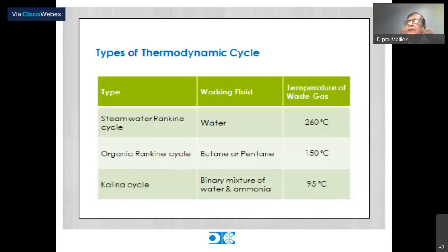That's true. But within this framework of temperature boundaries, there are other technologies which are also getting developed. One is, instead of using steam as a working fluid, we can use ORC, which is called organic Rankine cycle, with pentane as working fluid. There are quite a few plants, and a new Kalina cycle has also been developed, where ammonia is working as the working medium. There is one plant in Pakistan which is producing about 7 megawatt of waste heat recovery from Kalina. For just your information, within these temperature boundaries, ORC efficiency is about 35–36%, and with Kalina cycle, the efficiency will be around 60–65%. But again, both these technologies are still not in the mature stage.